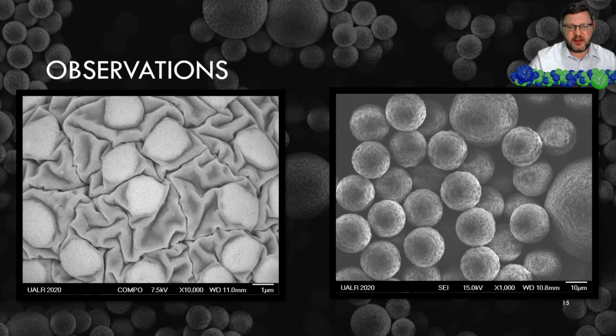Again, the image to the left is another backscatter image. You can see those denser, brighter spots of yttrium, and the smoother carbon resin areas around them. I do believe that the spheres, which we had to let decay for about 6 months to be completely inactive with no radiation in these samples, were affected by being left in the sterile water for such a long time. It did affect the surface of the resin. At least it gave it that more raisin-like or folded texture.